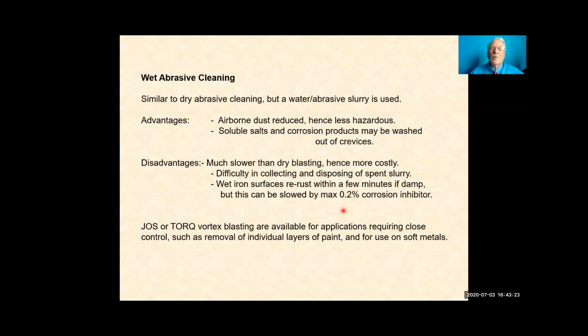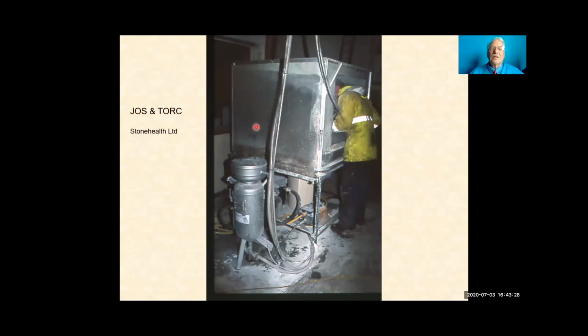This is one of the processes for wet abrasive blasting. It's a patent process. They come under different names, JOS and TORC and others. But here, the nozzle has a spiraling action. So instead of the grit coming straight out, it spirals. It acts as a sort of scouring. So it's very controllable, and you can take individual layers of paint off. You can take corrosion products off the non-ferrous metals like the patina off brass and lead. Very good. And we use it for the non-ferrous metals in particular, but it's good for ferrous metals too.